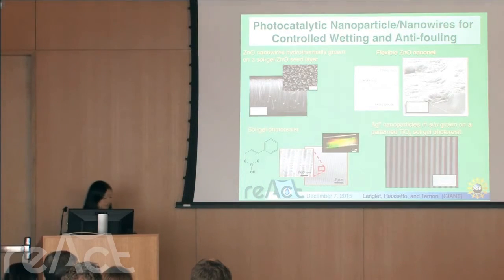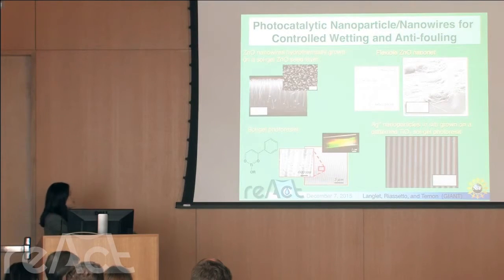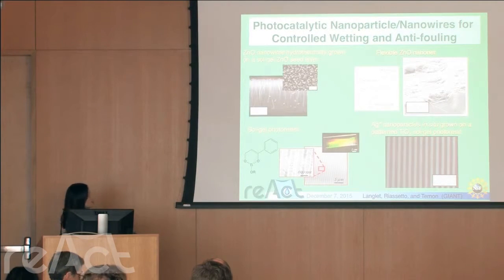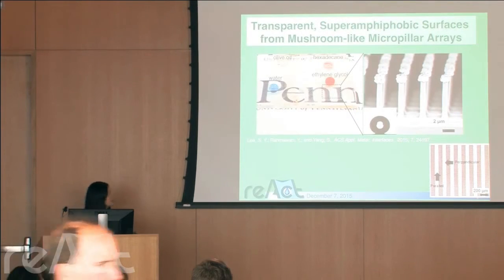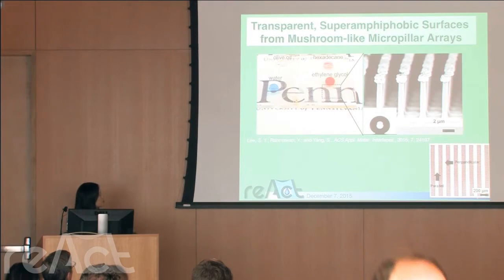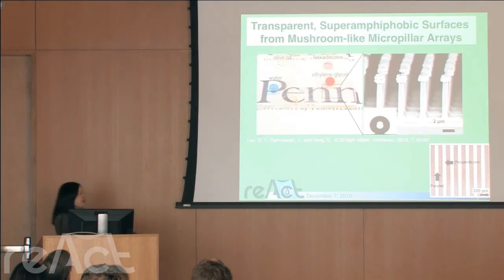And further, they can design a material to make them photopatternable. So you can pattern these kinds of regions and pattern these surfaces. Which will be a great synergy between Penn and the giant, by patterning these different kinds of nanowires, nanowire mesh, introducing different kinds of surfaces. We can put in different materials. Just to give you one example, we patterned the surfaces with these high aspect ratio pillars, and then we can purposely decorate those surfaces with nanoparticles. Imagine we can also do this decoration with nanowires, nanowire mesh.